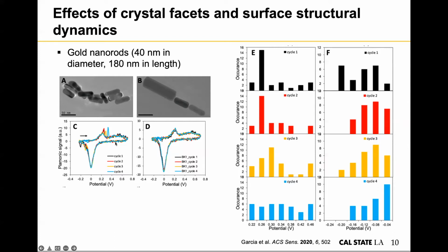The different colors actually represent different cycles. So we run 4 cycles, and this is another interesting thing we observed. Even for the same particle going through the electrochemical reactions, we see that the peak is not staying at the same location, which might suggest there could be surface structural dynamics going on there.